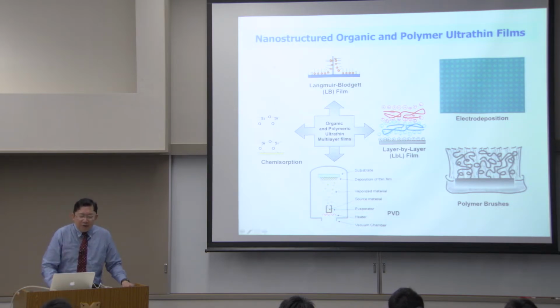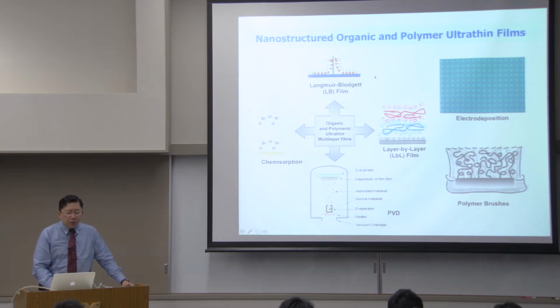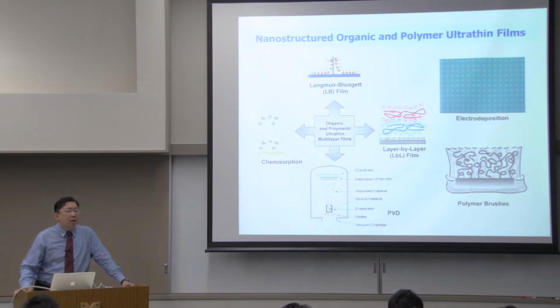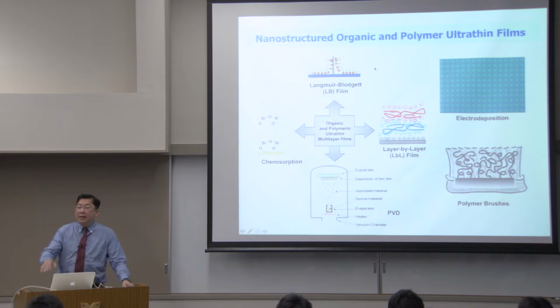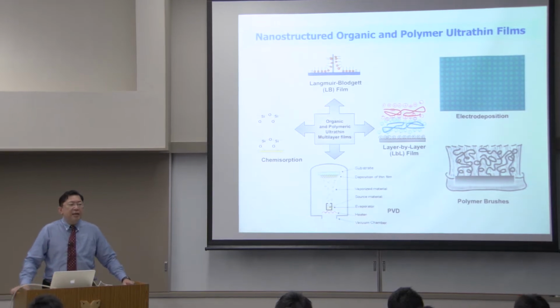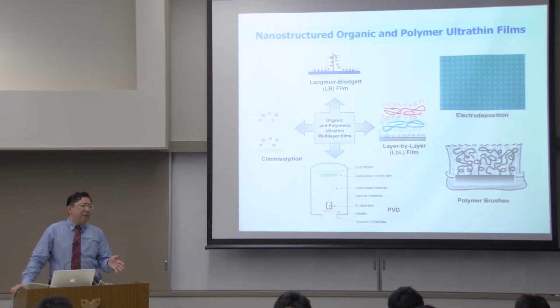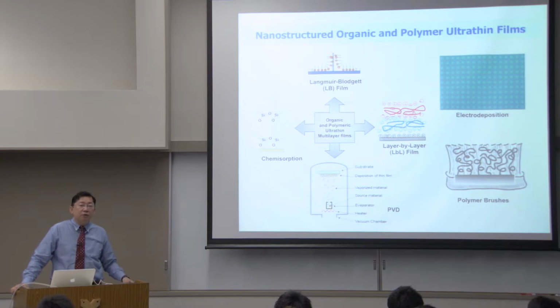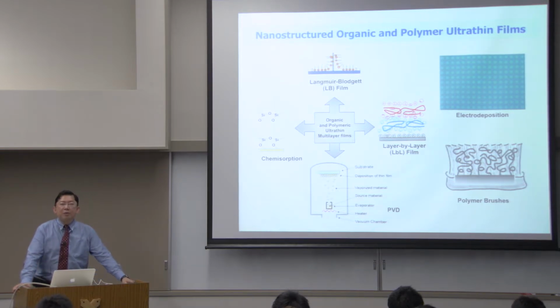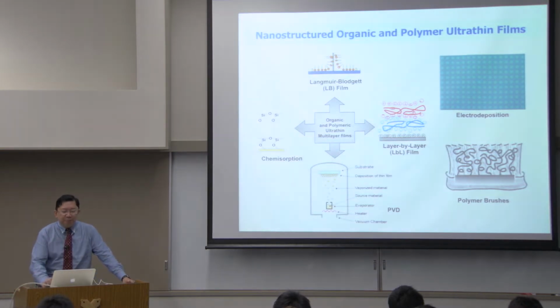Another way to modify a surface at the nanostructure level is to deposit a very thin monolayer of surfactant or polymer, what we call a Langmuir-Blodgett film. This means the material has to be equilibrated at the air-water interface, and then it can be picked up by vertical or horizontal drawing, which we call Langmuir-Blodgett or Langmuir-Schaefer.